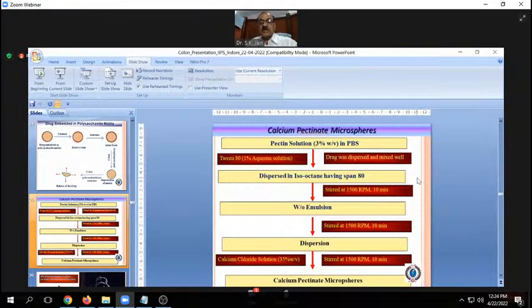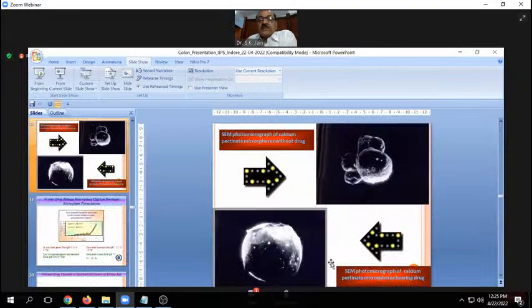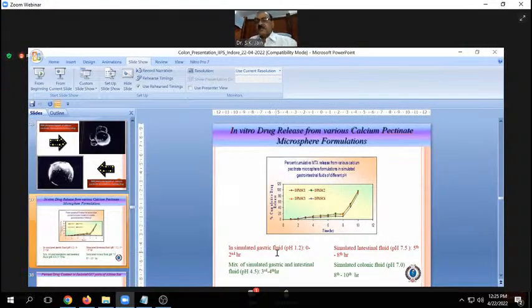In this dispersion, we add 35% calcium chloride solution and stir it continuously for 10 minutes. Because of the presence of calcium ions, the pectin will react, and the calcium pectinate microspheres will be precipitated. So you will have solid microspheres, and we centrifuge them and wash them properly. These are the photographs of the calcium pectinate microspheres. This is without drug, and the lower one is with drug. Then, just to ascertain whether the drug is released in the upper part of the GIT or not, in which part the drug is released.